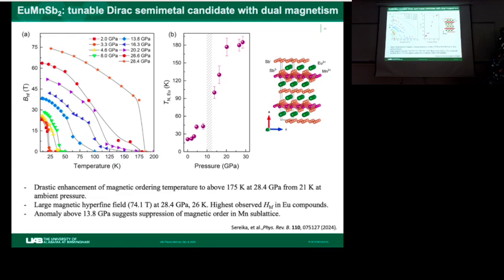Okay, so in this compound here, as I introduced earlier, what we found was under high pressure, the magnetic ordering temperature goes up almost tenfold. It started at 20-something Kelvin and goes almost above 180 Kelvin with only 28 GPa.